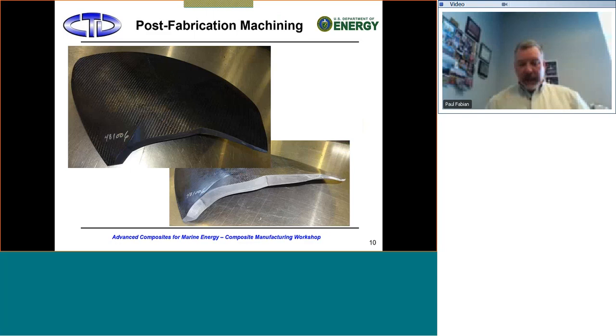Following that, in this case, we did some post-fabrication machining. So the resin flash was taken off, but we had some very high tolerance dimensions that we needed to make on the lower edges of the blade. And so that was actually done with CNC machining. But you can see these are all of those fiber plies and now have become a solid composite. We have very low void content. We matched the fiber volume fraction that we wanted in these cases.